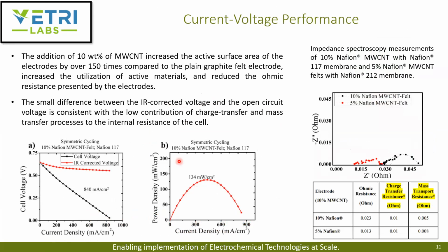And they recorded the current voltage performance. Initially I mentioned that they used multi-wall carbon nanotubes on this graphite felt to modify it so that they can have an active surface area 150 times higher when compared to the plain graphite felt electrode. So in this way, you can increase the utilization of the active materials and reduce the ohmic resistance presented by the electrodes. So to identify the contribution of the ohmic resistance, charge transfer resistance, and mass transport resistance,